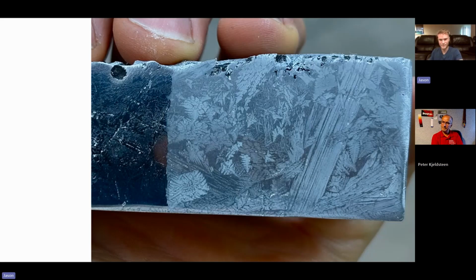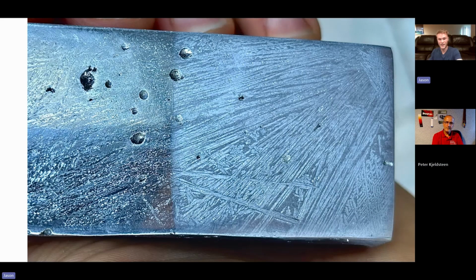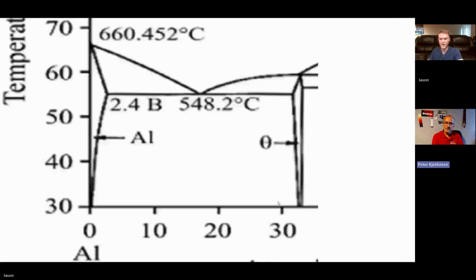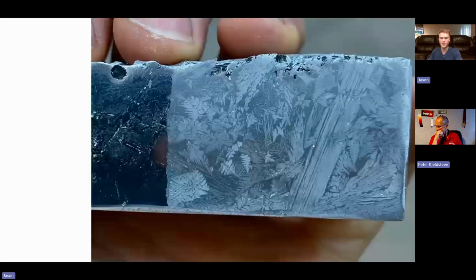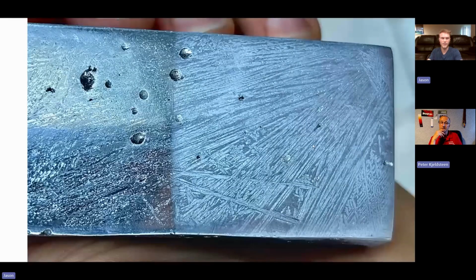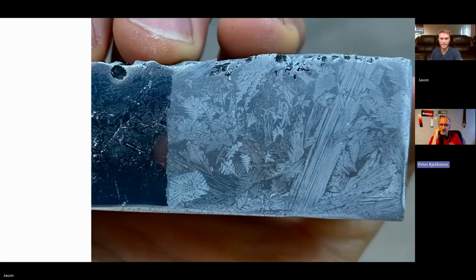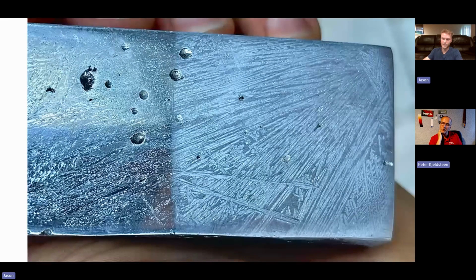So this is one composition. This is a second composition. This is only like a 5% differential in copper. I think I moved to the left. So at first I had approximately 30, and then I had approximately 25% aluminum. Again, those aren't the exact numbers. They're in the video. I've forgotten by now. But you see, you're in the alpha theta coexistence region, but you have dramatically different microstructures, and almost no dendrites left. And same cooling pattern. Yep, same cooling.